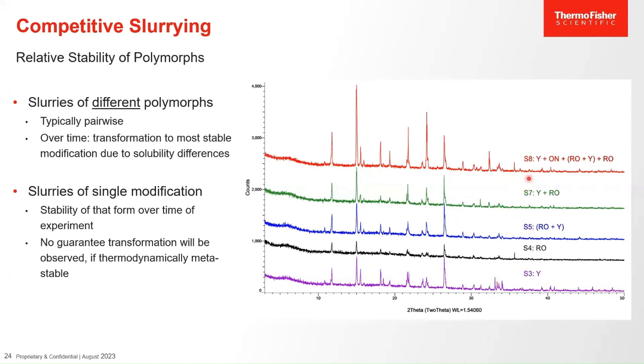Here we've done a 4-component competitive slurrying, 2-component competitive slurrying. This was suspected to be a mixture of forms from a single crystallization experiment. And this is a single form slurry. And as you can see, this shows you the end point of the slurrying. All of these powder diffraction patterns are identical to the yellow form. And with that, the yellow form is the most stable of all the other modifications that were generated here.